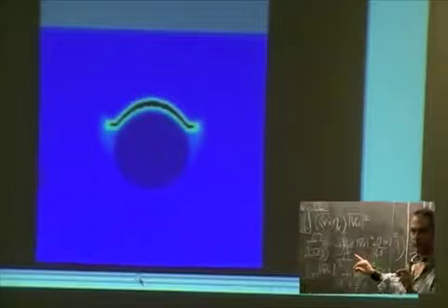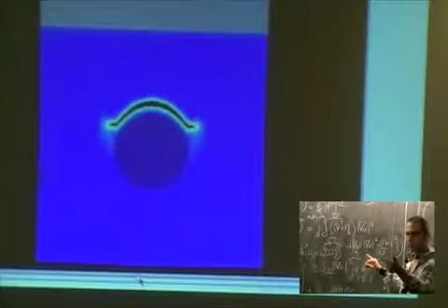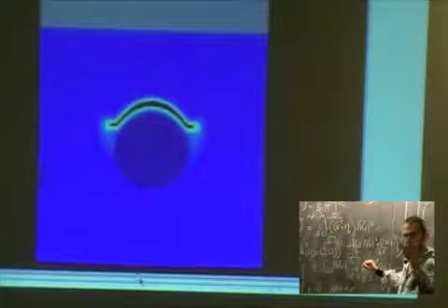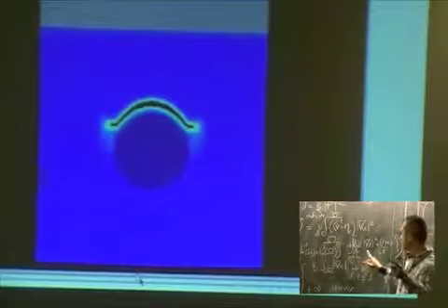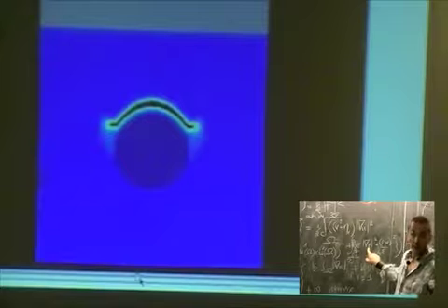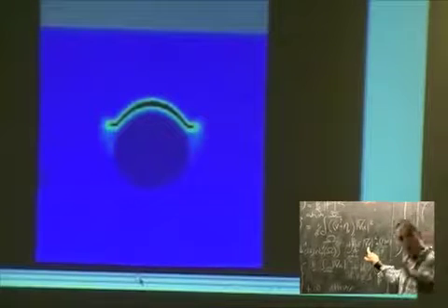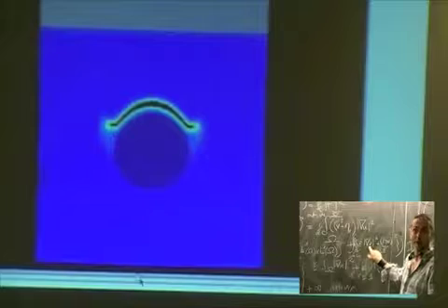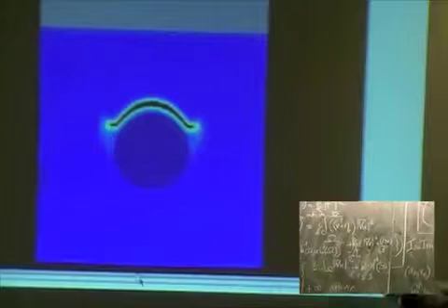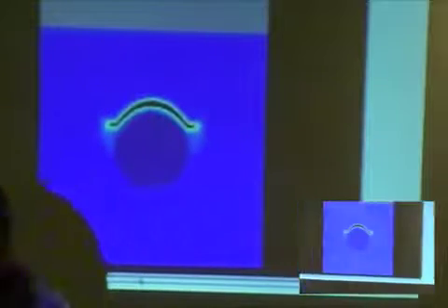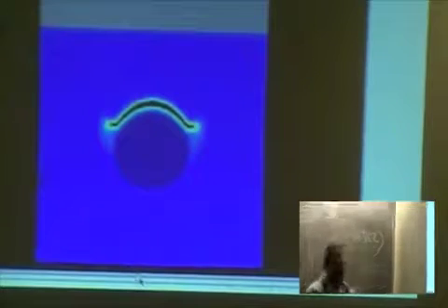I enforce it by saying that from one time step to the next, I forget what V epsilon was previously, except where V epsilon was less than 10 to the minus 2, where I put it to be 0. So that's why that light blue here has disappeared. Once it becomes 0, it remains 0.